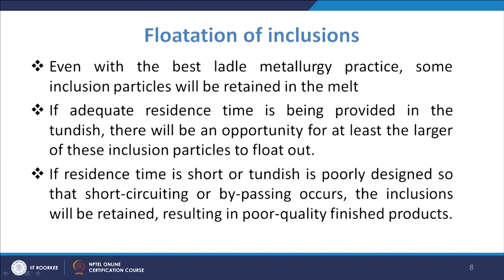Once inclusions enter the solidified region of the mold, they are trapped and become part of the product, leading to rejection. Short-circuiting must be avoided; it often occurs due to poor tundish design or improper use of flow modifiers. The average residence time must be checked to ensure inclusions have sufficient time to float to the top surface of the tundish where they are trapped.